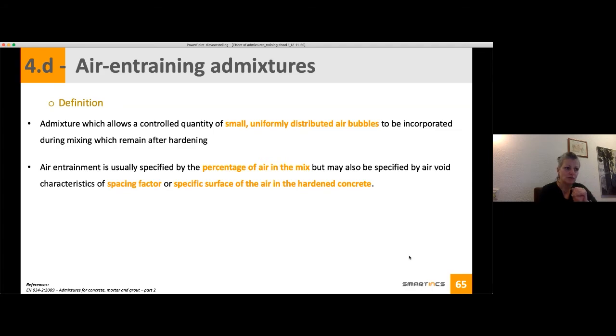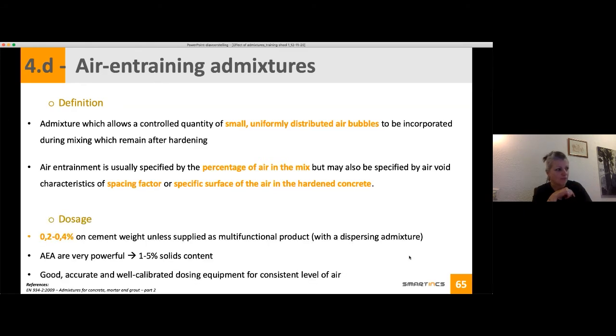And so you have requirements. It's specified how much air you should have in your mix, but also what the distance is between two air bubbles. This will give an indication of the freeze-thaw resistance. If we look at the dosage, it's also low, 0.2 to 0.4%. What we really need to take into consideration when we talk about air entraining admixture is that they are very powerful.